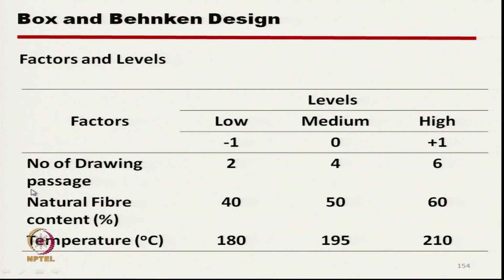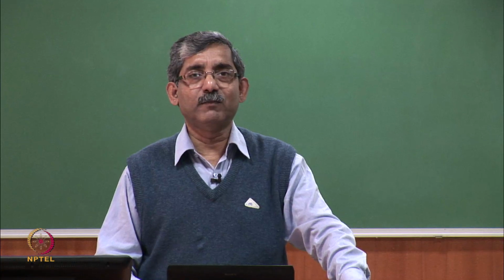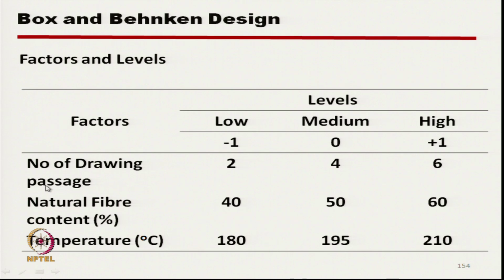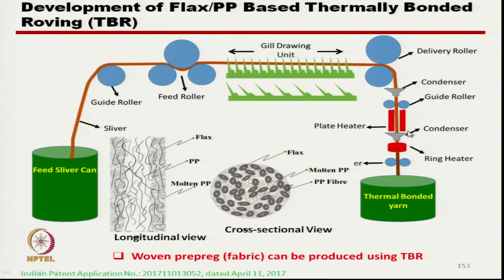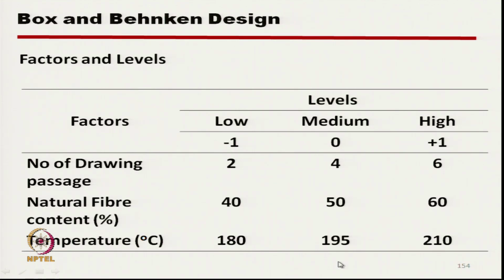Now, the main question is, what about the uniformity in blending? So, to have uniform blending, we have used a number of drawing passages. So, 2 passages, 4 and 6 passages, 3 passages we have used here, and also we have varied the natural fiber flax content in the thermally bonded roving, which is 40%, 50 and 60, 3 different natural fiber contents we have varied, and also we have used 3 different temperatures. So, that the proper melting of polypropylene takes place. This temperature is the temperature at this heater, it is 180 degree Celsius, 195 and 210.